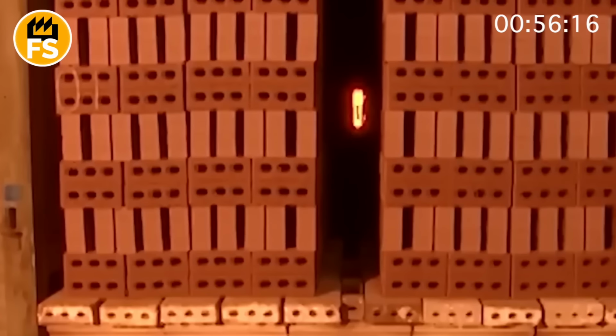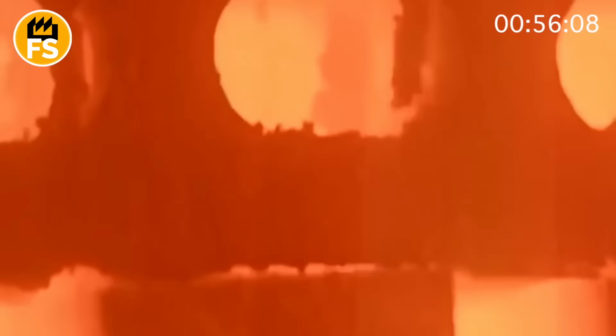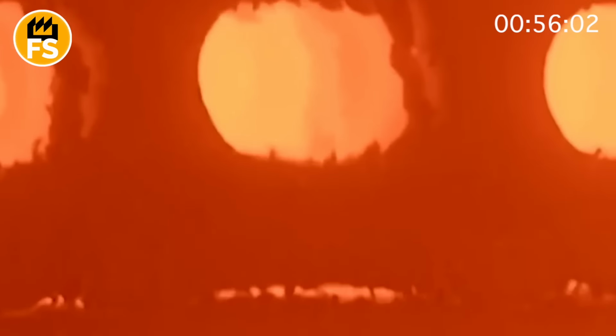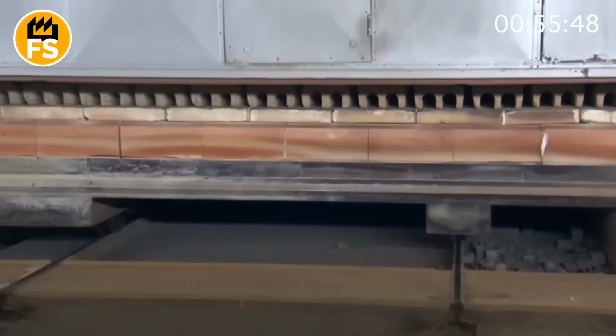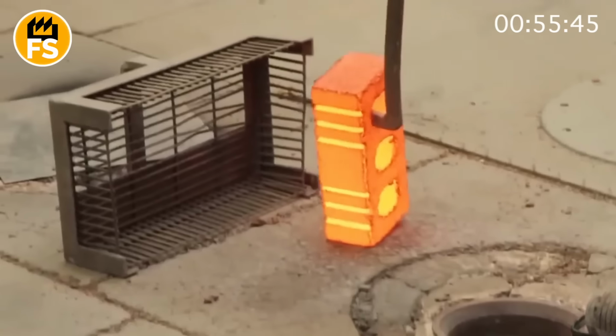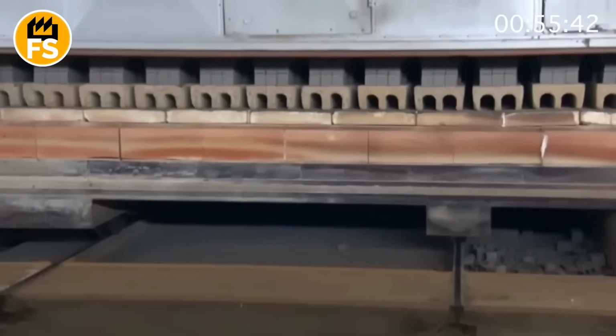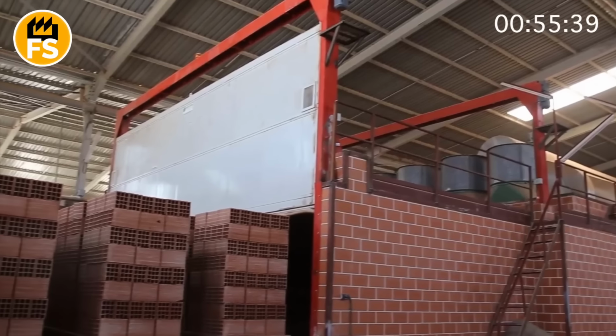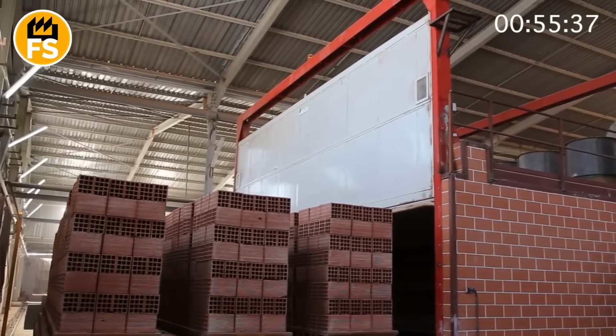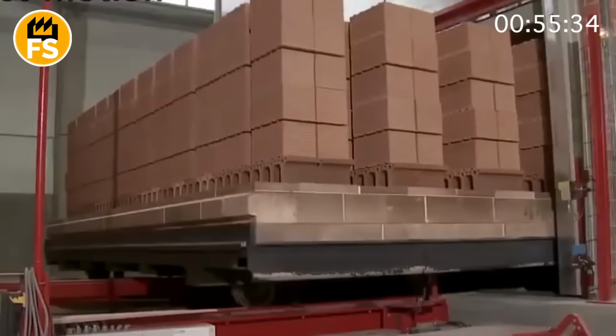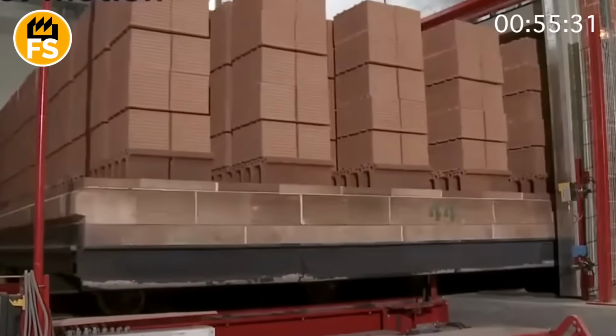First, it enters a preheating zone, where its temperature gradually rises. Then, it enters the central firing zone, into the very inferno. Here, the temperature reaches 2,000 degrees Fahrenheit. The chemical miracle called vitrification occurs. The clay particles begin to melt and sinter together, forming a strong, glass-like structure. It is at this moment that the brick acquires its final color, which depends on the mineral composition of the clay and the firing temperature, and its incredible strength.